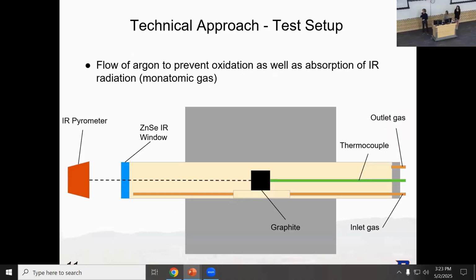This is a little cartoon that we showed last semester of what we predicted our experimental setup to look like, in which we have our graphite sample sitting in the center with an alumina plate supporting it to get it in that viewing distance. On the right side, we have a custom end cap with our thermocouple in to get the true temperature of the sample, as well as gas lines flowing argon through the system.